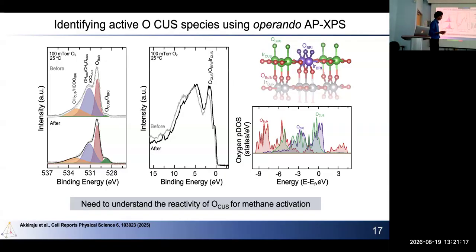We also looked at the valence band, where again, this is before cleaning and this is after cleaning. Cleaning is where we remove any carbonaceous impurities that form in the reaction chamber. We see that these species become more clear after cleaning. Similarly, the valence band edge also spikes up, suggesting that this feature belongs to a special oxygen feature that only shows up for rutile oxides.